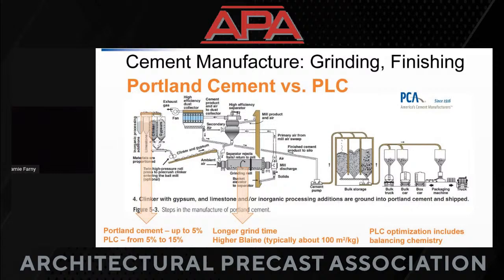Where the PLC is just slightly different in formulation is that we can go from 5% up to 15% of ground limestone. So that's one key difference right here, the proportion of the materials. The other key difference is that we get a longer grinding time. Again, we're going to be making a very fine powder out of this.